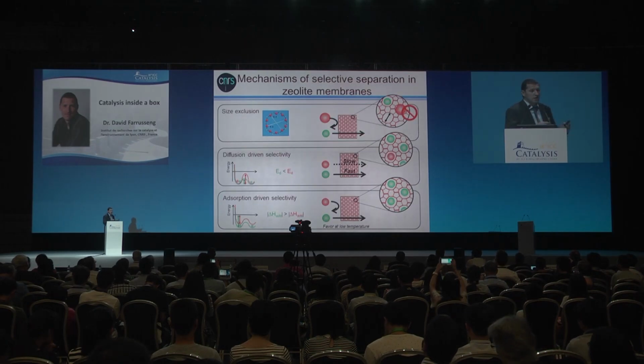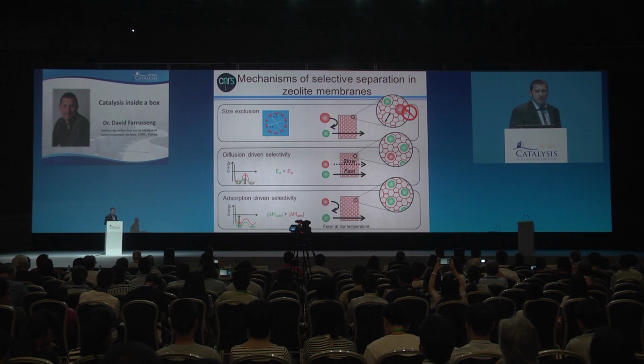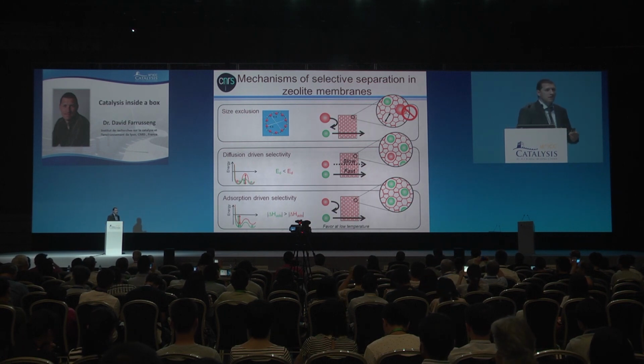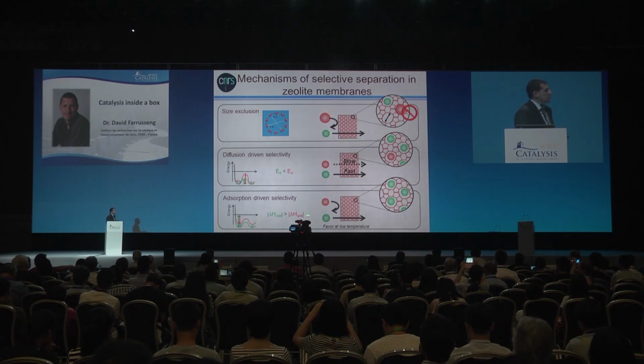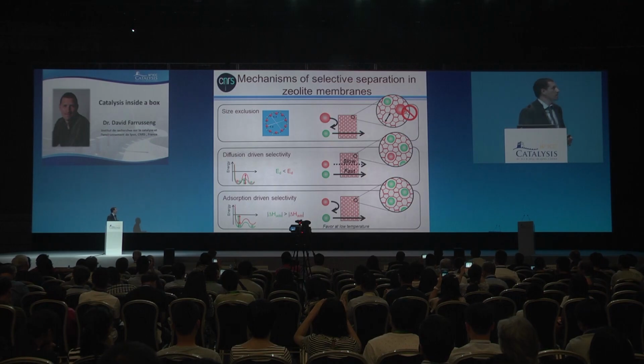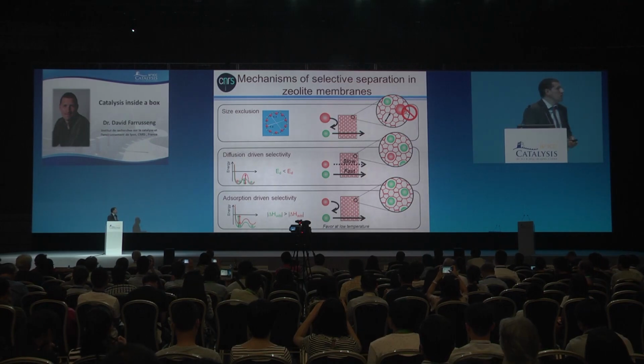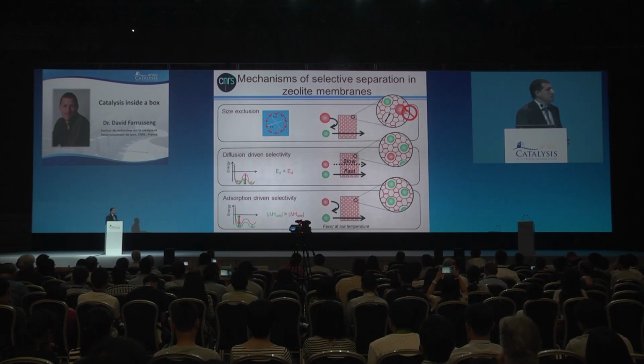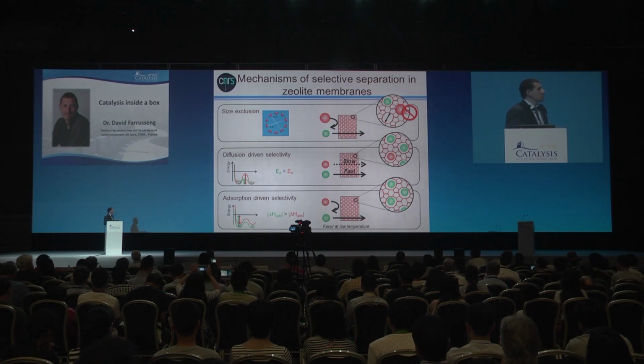And here are the 3 mechanisms that I know in the field of zeolite membranes for achieving high separation and high selectivity. And for each case, I will show one example. The first is obvious, it is size exclusion. It is when one substrate is much larger than the pore window of the zeolite. It's obvious you're going to have a size exclusion.